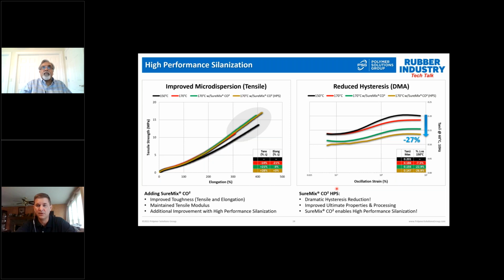Of course, the whole goal of going to the higher temperature was to drive the silanization reaction and to improve the hysteresis and fuel economy of the compound. Going from the black curve to the red curve on the right, the hysteresis by DMA, you see that reduction in the hysteresis. If you could do that in production, if you could mix that compound, you would do it because that's going to be a benefit in your tire. You're going to see improvement in fuel economy in those tires.